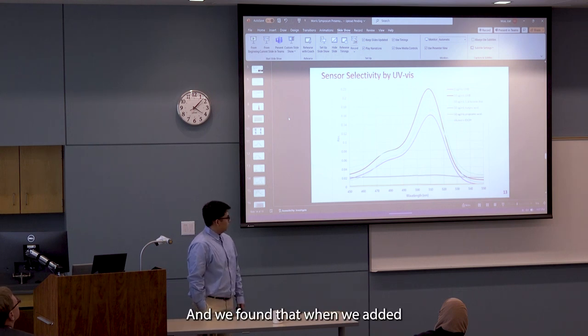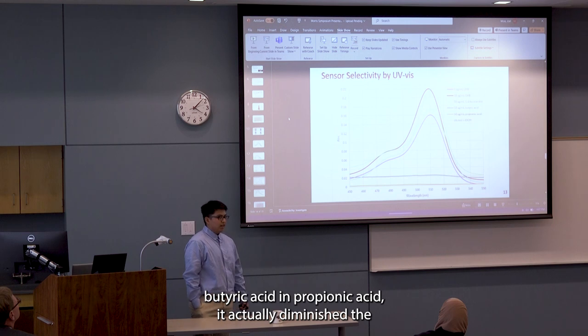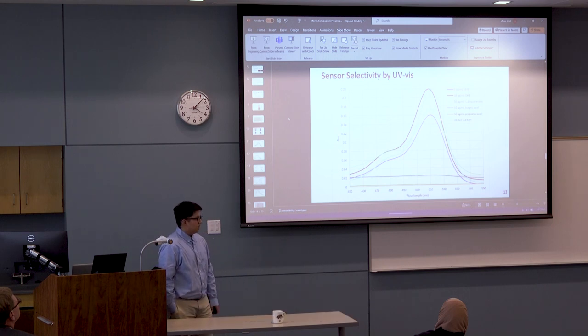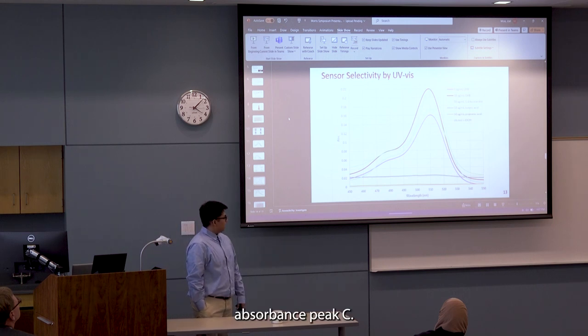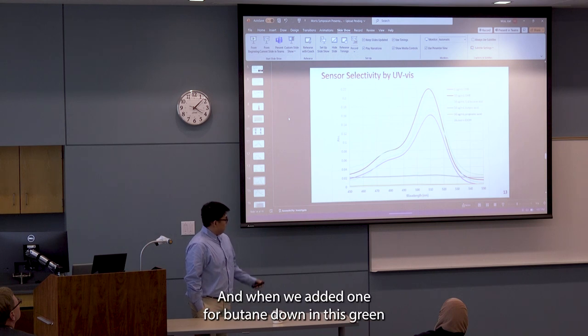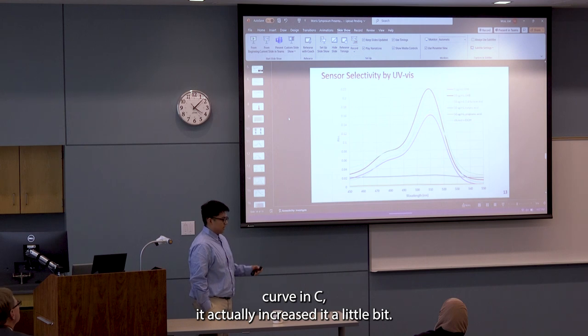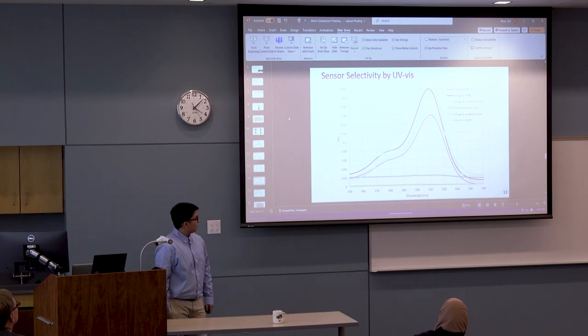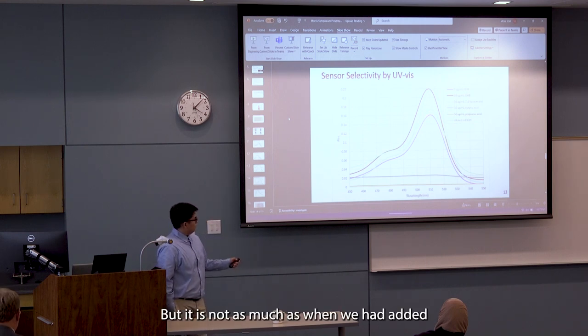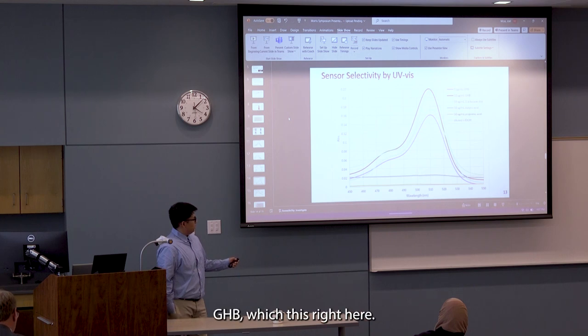And we found that when we added butyric acid and propionic acid, it actually diminished the absorbance peak seen. And when we added 1,4-butanediol in this green curve, you can see it actually increased it a little bit. But it is not as much as when we had added GHB, which is seen in this red curve.